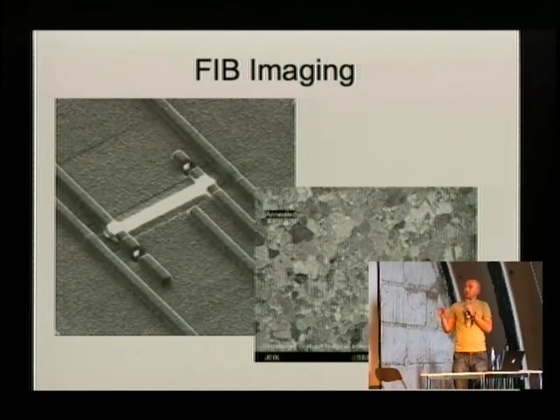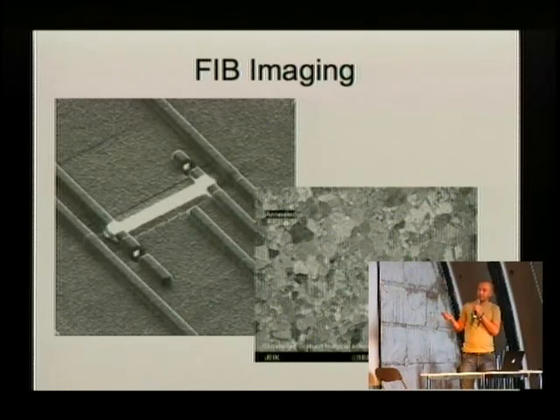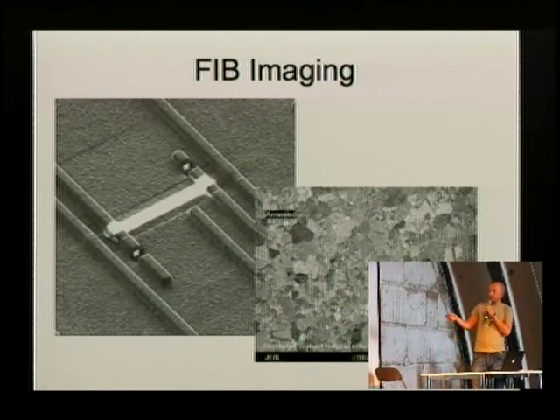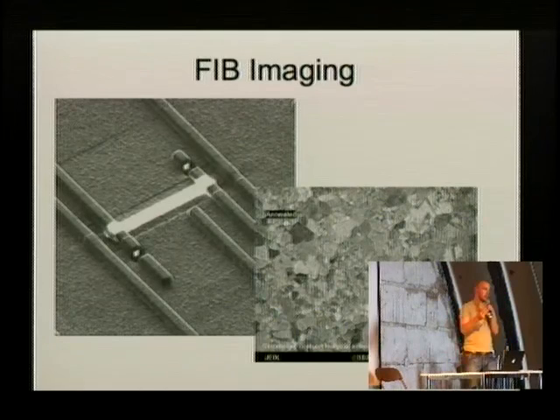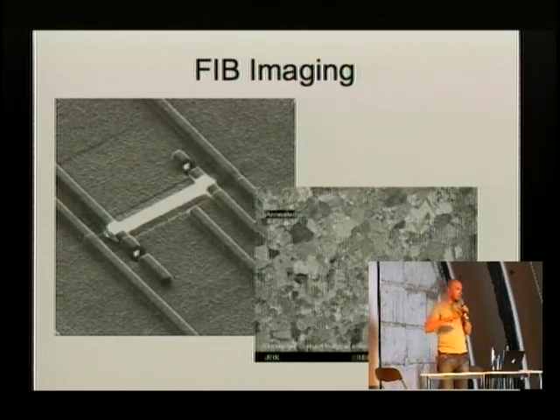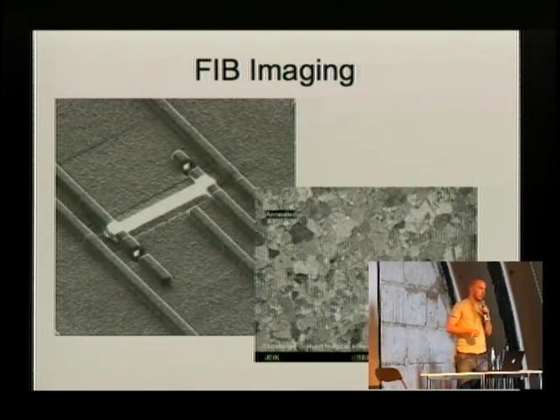This is pretty straightforward. If you have a very low dose, you get some nice signal. It basically looks like an electron microscope picture. Here we have some metal lines and nothing much different than an electron picture. There's only one effect. If you look at metals that have some granular structure, even though the metal itself is flat, you see all these small islands. This is because the metal lattice is oriented differently in the grains of the metal, and you get some channeling effects. That reduces your secondary electrons, and although the surface is flat, it looks structured in the picture.